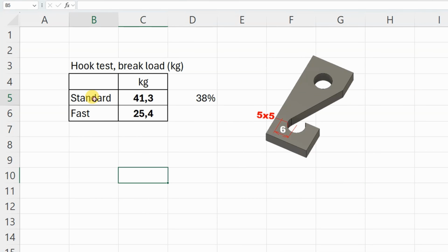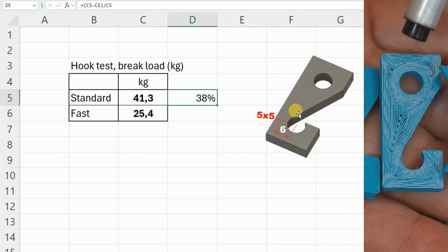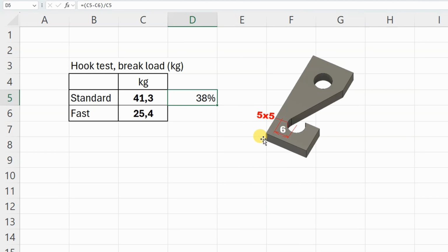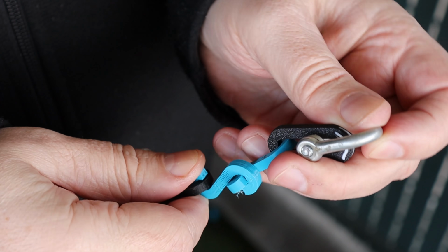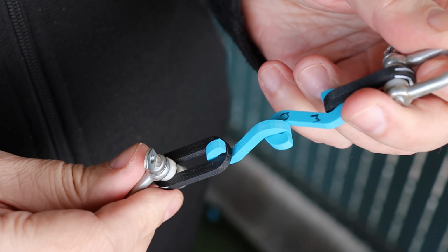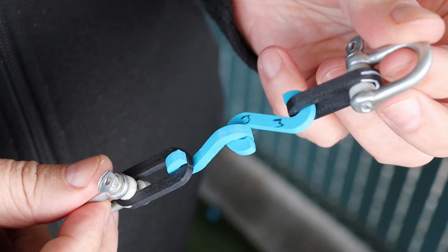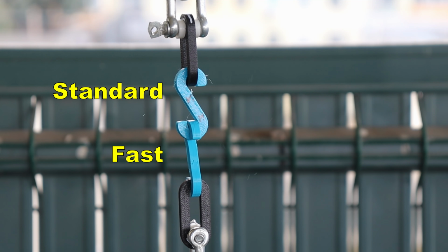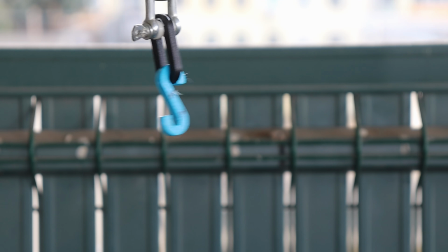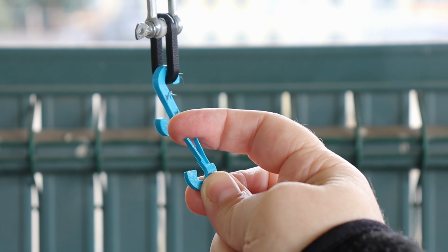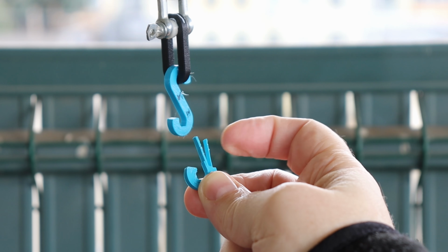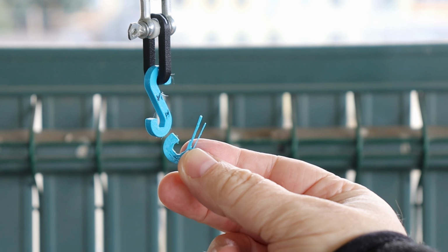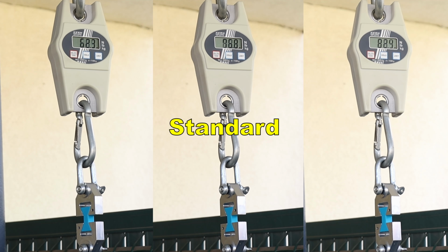In this test, the standard speed was stronger by approximately 38%, but here not directly the layer adhesion is important, but the adhesion between the walls, and you will see this better in my next test. The elimination hook test, which is more interesting if I have several objects, and the weakest always falls out. A little bit bad angle for the camera, but with my eyes I could clearly see how walls detach from each other, so in this case the wall adhesion is very important.